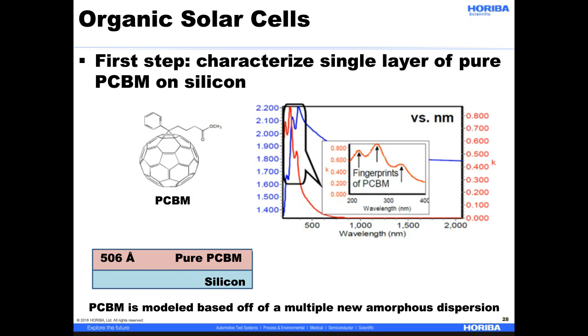Just as we did in the last example, we'll break this down step by step with single layer samples. First you have to characterize a single layer of pure PCBM on silicon. We ended up with a thickness of 506 angstroms of pure PCBM on silicon. Over on the right are the optical constants for that PCBM, and you see what we call the fingerprints of the PCBM, which are basically the peaks in the extinction coefficient, zoomed in a little bit there.